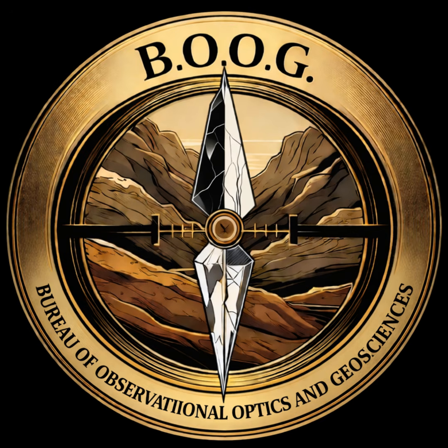Right, the star effect. In a star sapphire, that silk is arranged perfectly and is highly desirable. But in a standard faceted gem, an overabundance of randomly scattered silk makes the stone look cloudy, gray, and visually dead. It just looks foggy. When the sapphire is heated to 1800 degrees, the immense thermal energy forces those solid rutile needles to literally melt and dissolve back into the solid solution of the corundum lattice. The physical obstructions vanish, and a stone that entered the furnace looking like a cloudy piece of gravel emerges crystal clear.